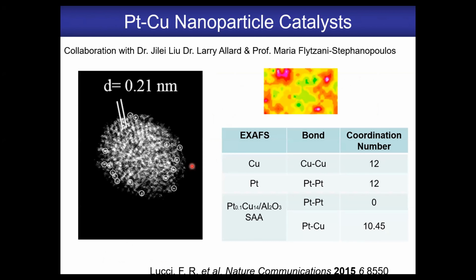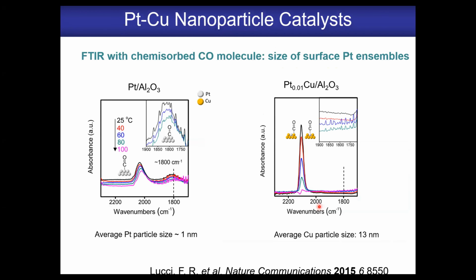And that's where my late colleague Maria Stephanopoulos in her group contributed massively to this project in demonstrating the first single atom alloy nanoparticle catalysts. This is a TEM image of a platinum copper catalyst. This is XAFS data showing the dispersion of the platinum, that there's no platinum-platinum bonds detectable. And the strongest evidence for it being a single atom alloy catalyst is infrared spectra of CO, where on the 1% platinum copper single atom alloy catalyst, we see only a peak in the infrared spectra for CO atop platinum.